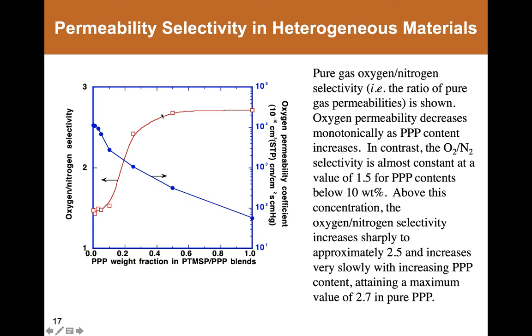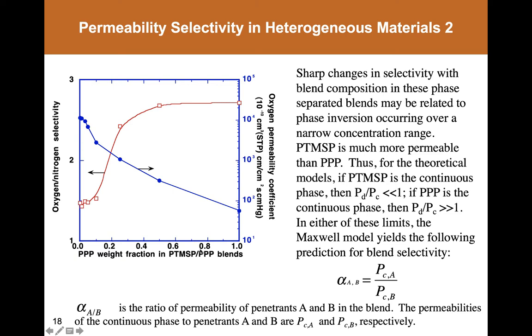And this indicates the region where the blend is now continuous in polyphenylpropyne, and PTMSP is a dispersed component in that continuous matrix. The step change in selectivity is often a strong marker for phase inversion in phase separated systems, and it's often about as sensitive a marker of that as you'll see.